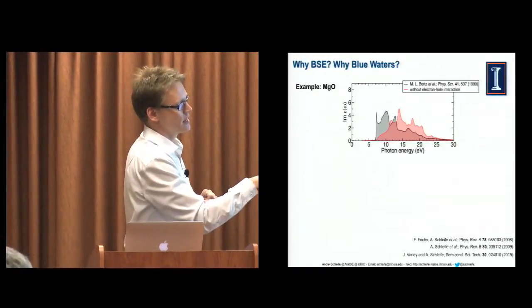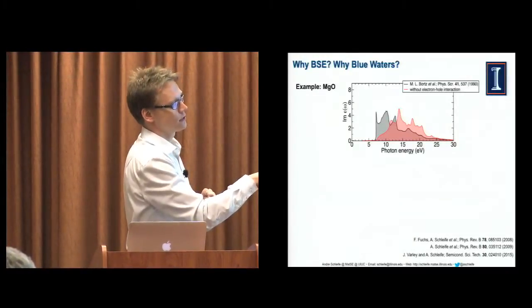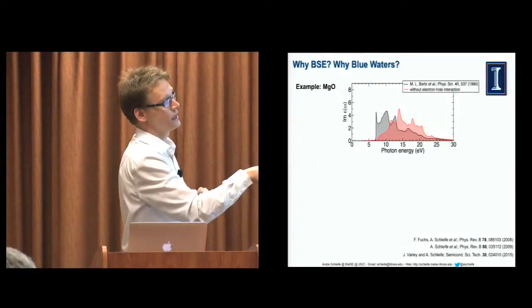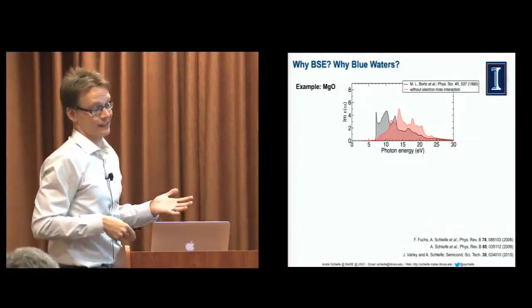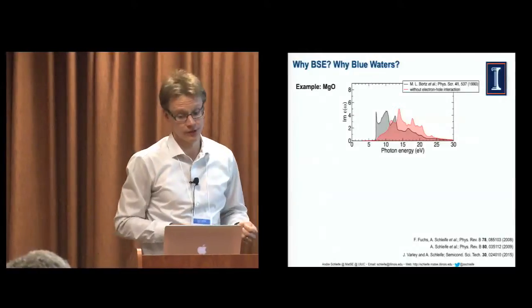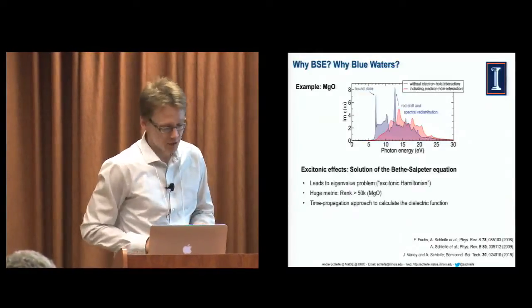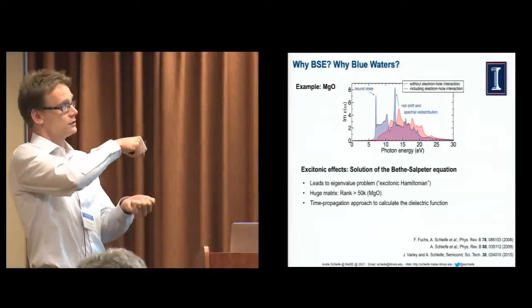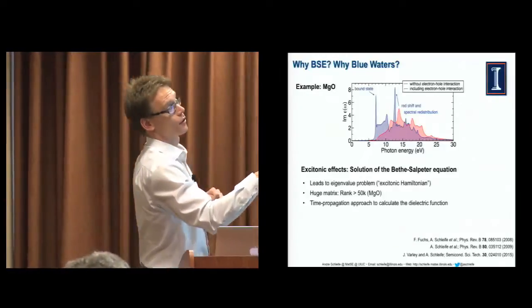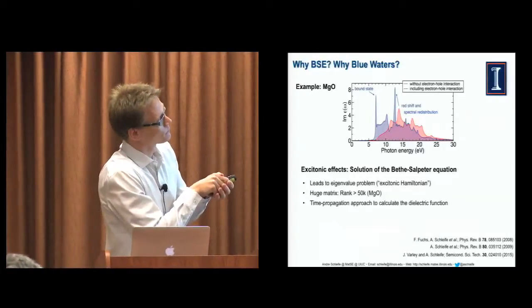Maybe the band gap is kind of right, because the onset here is at roughly the same energy between the two curves, but then at any other photon energy, there's practically no agreement, right? And so you could not really predict an optical spectrum. Now, if we take into account this electron-hole attraction that I mentioned, then we get the blue curve, right? So you can see it looks vastly different.